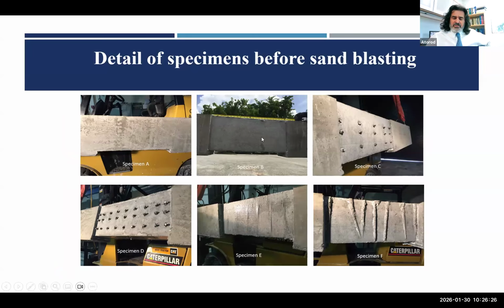And we tried to see, okay, if I have a damaged area, what do I need to do in order to get the UHPC to be attached to the normal strength concrete? What we found out is that we tried to put some mechanical devices to give a good bond. There is no need for that. All you have to do is sandblast the area that you want to beef up its capacity, shear or moment, and expose the aggregate before a spray or cast in place. Make sure the surface is wet, and that's all you need to do.